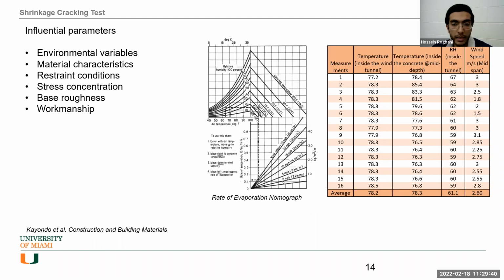And the same class contains the characteristics of your materials, your rebar, I mean, your reinforcement, and also your concrete: the cement content, the fiber content in the FRP, the water to cement ratio, the aggregate size, admixtures, supplementary cementitious materials, concrete temperature, fiber types, rebar surface profile. And each rebar has a different surface, ribbed or sand coated, or a different surface profile, which we cover in the second study in this presentation. And also each rebar has a different modulus of elasticity that can make some changes in the result.